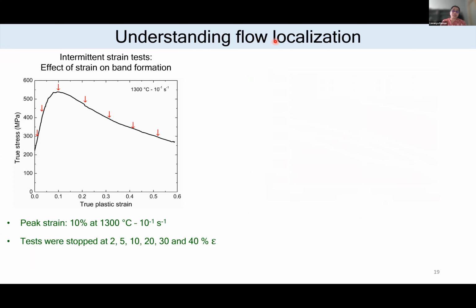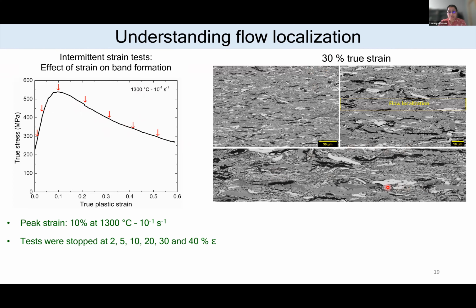Now to understand the flow localization, we did some intermittent strain tests. That is, we stopped the test at a particular strain and then quenched the sample to check the microstructure. Like that, we conducted tests at different strain levels. When we checked these microstructures, we were able to identify the flow localization only at 30% of plastic strain. Which means the flow localization happens somewhere between 0.2 to 0.3 of the true strain. In the literature, people have shown that usually this flow localization or the shear banding happens beyond 25% of strain.